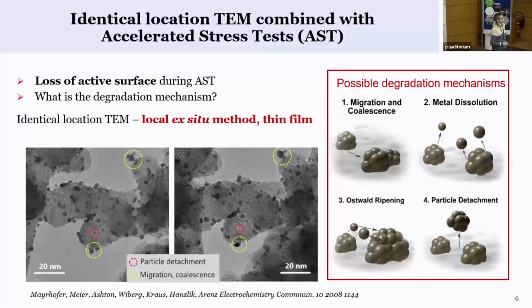So based on this, we try to distinguish different mechanisms you can imagine in a catalyst degradation process, like particle migration and coalescence that you might see here, that particles move on the support and then form a larger new particle. But you also have Ostwald ripening in electrochemical systems. You imagine that you form ions that then redeposit on larger particles. You have metal dissolution, of course, and also particle detachment, like here, that individual particles fall off the support due to, for example, carbon oxidation.